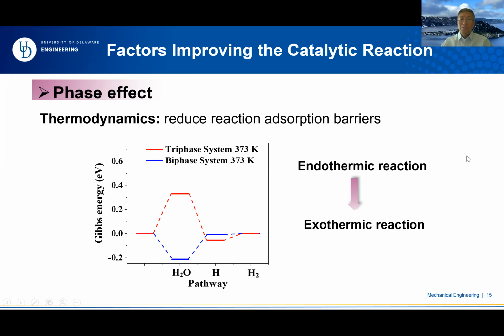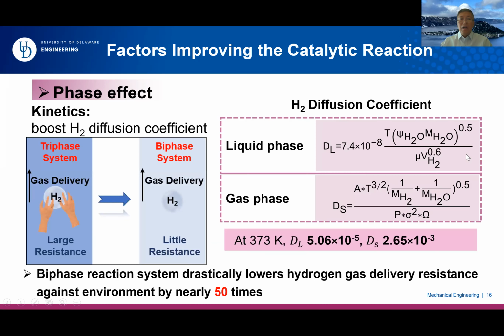So this is from the thermodynamic perspective. From the kinetic aspect, this phase change also dramatically boosts the hydrogen diffusion coefficient. So we simply calculated the hydrogen diffusion coefficient in both the liquid and the gas phases. You can see this diffusion coefficient increases by nearly 50 times if you simply change the phase. Okay, so that's significant,